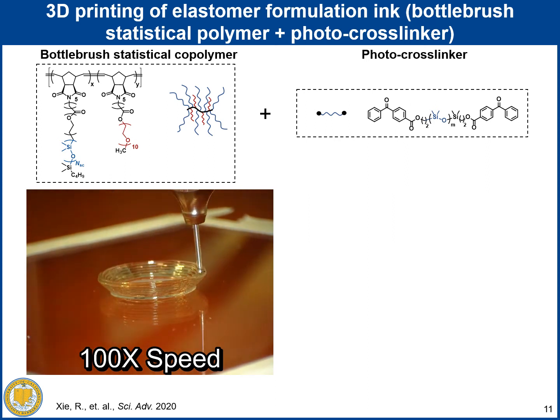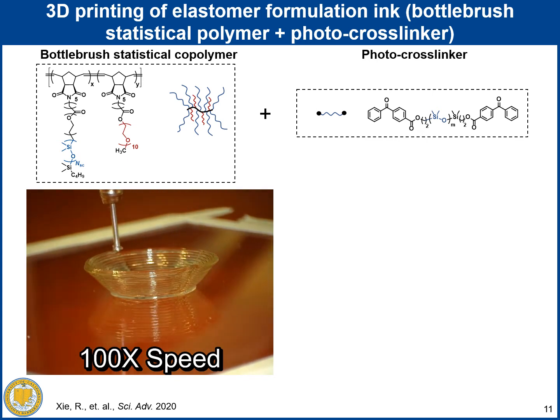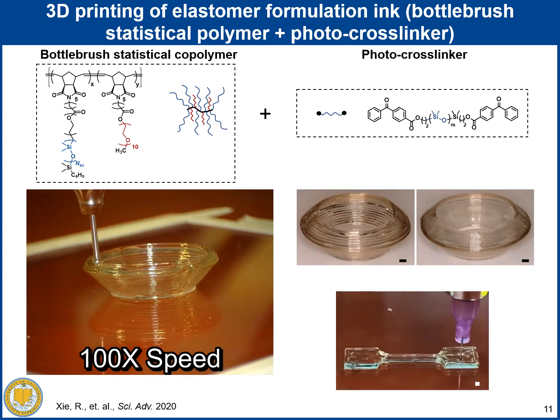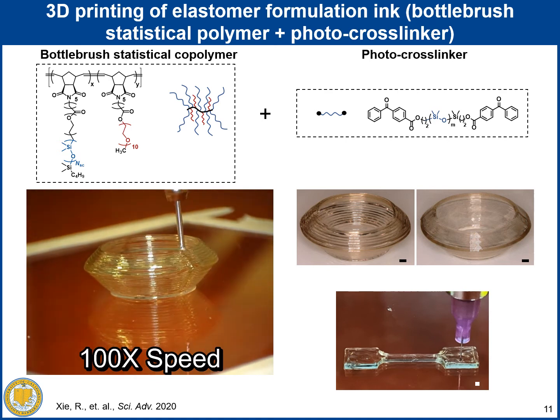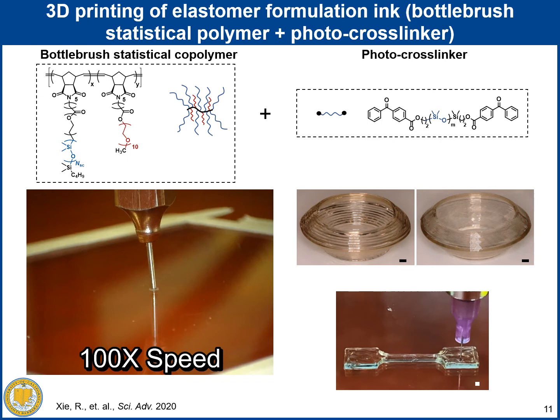This video is actually sped up by 100 times already, and the actual whole process takes about 40 minutes to complete. We also printed another bowl with a finer resolution, as shown for comparison, and also another dog bone specimen with a finer resolution, so that we can compare the mechanical property between the printed part and the molded part later.